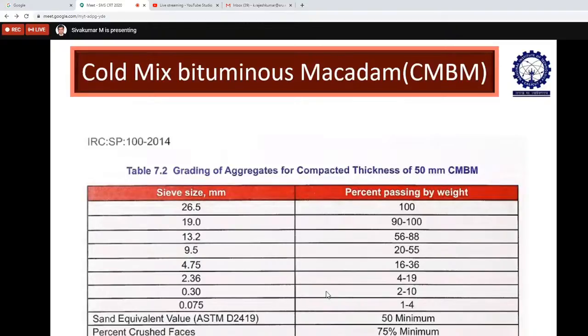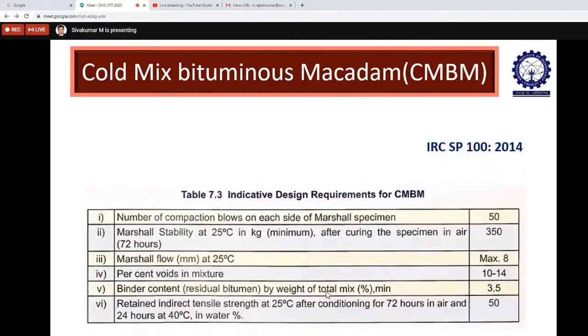So when we design the mix criteria, we can follow IRC SP 100, and the methodology as well as the technology is also available for construction. And these are the indicative measures. If you remember, the Marshall stability value at 60 degrees, that is the pavement temperature, should be 900 kg. Whereas for cold mix, it is a minimum of 350 at 25 degrees C. And the Marshall flow value at 60 degrees has a maximum of 4 mm and a minimum of 2 mm. Okay, the acceptable limit is 2 to 4.